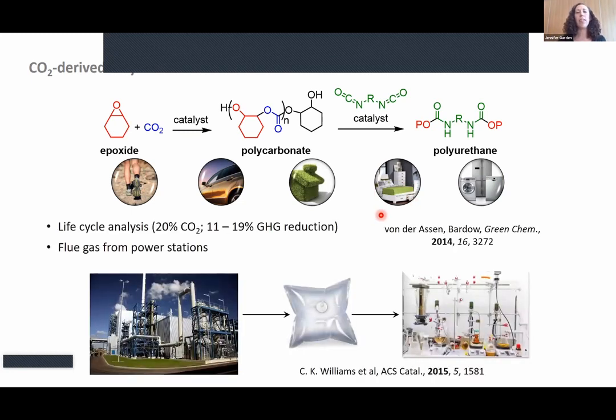So life cycle analysis has also been done on incorporating 20% of carbon dioxide into the structure of a polyurethane. And again, this reduces the greenhouse gas emissions. Something that's been quite interesting is that the carbon dioxide taken from flue gas, so from power stations, has been tested with these processes. And while there are some impurities in these source of carbon dioxide, some catalysts do show some signs of being able to tolerate some of these impurities. So there's some early promise in terms of this strategy for being able to make materials from waste CO2.